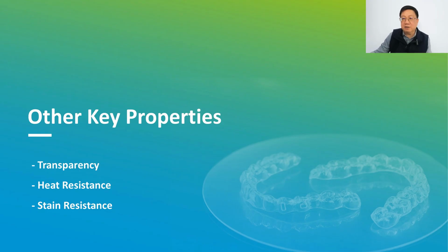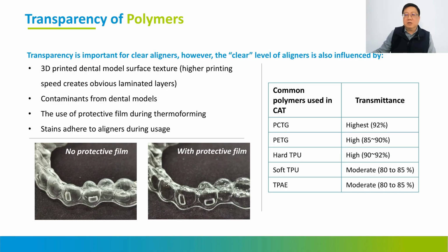This comes to other key properties. We'll talk about transparency, heat resistance and stain resistance. For transparency, right now we spend a lot of time to provide the best protective film regarding stickiness and other dental sheet issues, because you need to make sure that during the forming process it will not delaminate, and also make sure it is easy to take out after the process. You need to take out the protective film without it sticking to the aligners. So how to make a good protective film is very important. The thickness of the protective film is also very important.